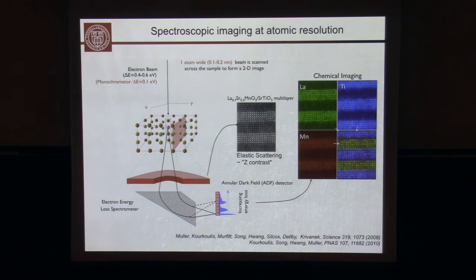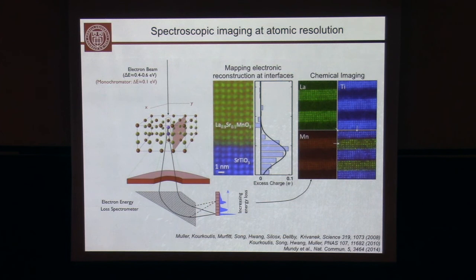While I will not talk about the details, today the precision of our measurements is such that we can extract extremely small variations in charge. And so here we have looked at a manganite grown on top of a strontium titanate. In this case, when you measure the charge distribution across this interface, you see an accumulation of charge right at that interface. And when you look carefully, the maximum number of electrons in this layer is about a fraction of an electron, so 0.1 electrons.